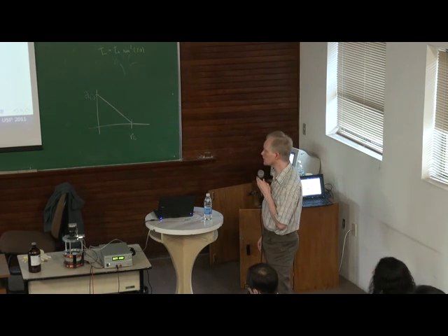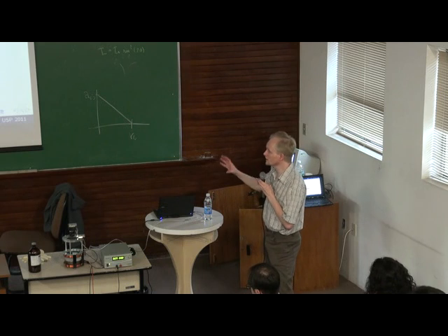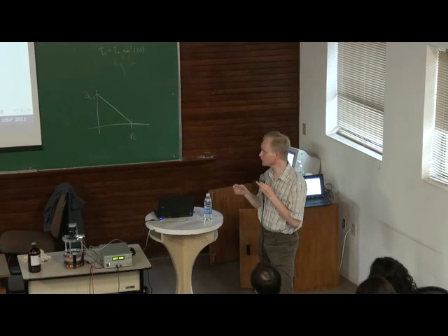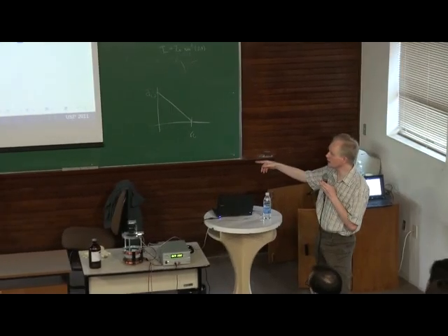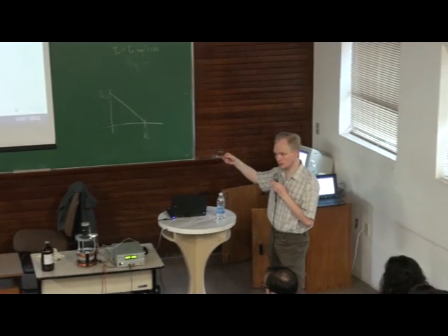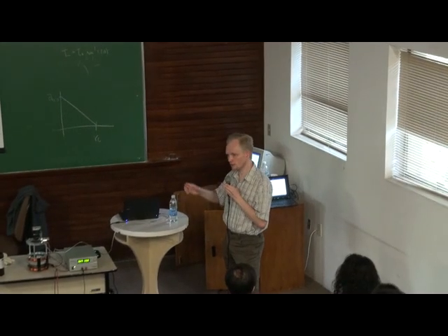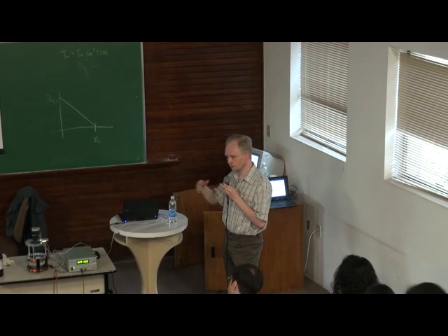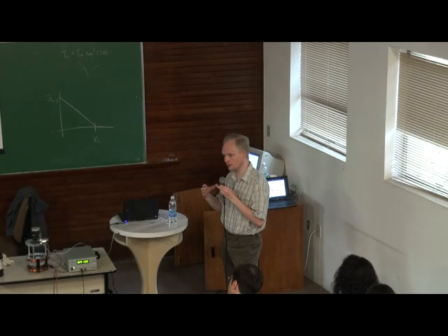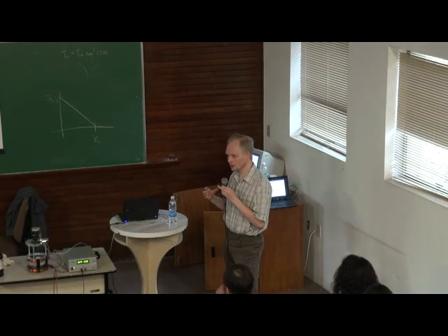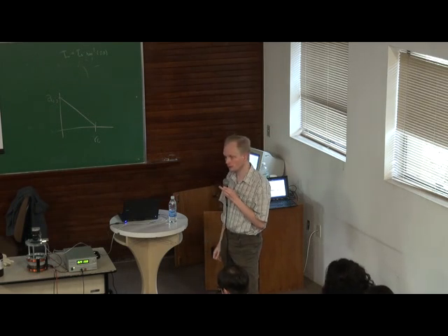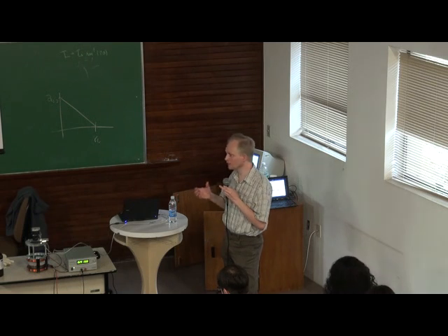Or I could look at the surface energy between the liquid and the head group maybe, or maybe the tail, between the tail and the liquid particles. I could calculate that energy and see how it depends on concentration. Because when the tail groups are in the micelle, they'll be screened from interaction with the liquid. So that should drop at a certain concentration. So I can measure the micelle concentration as a function of the interaction potential in many different ways. I just cannot tell you what it is a priori.